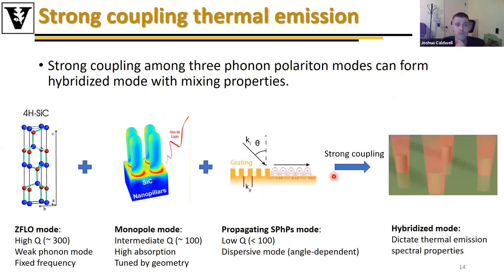So to start probing this, we started looking at some of these strongly coupled systems within silicon carbide, exploiting these zone folded modes, right? And so what we find here is we're basically taking the zone folded LO phonon, we're coupling it with a monopole mode, which is a nominally localized mode with some propagating character. But now taking these resonant particles and separating them out within a two-dimensional grating that can provide diffractive effects in the long wave infrared, giving us this hybridized mode that we can then hopefully use to design the thermal emission properties and in the end, hopefully result in a means for electrical pumping of these devices.